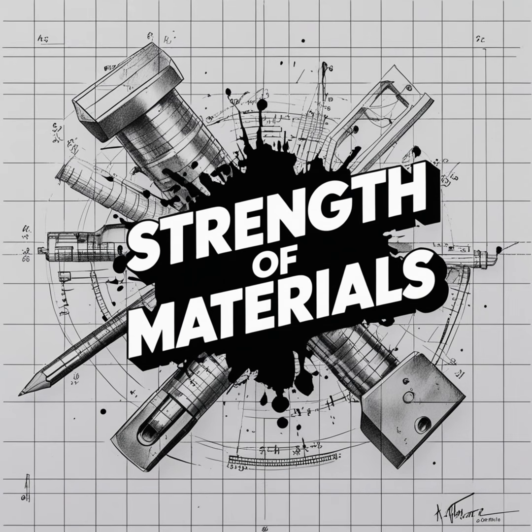Then you draw path 2. Path 2 is a massive loop drawn far away from the crack, way out on the outer edges of the metal block in the elastic region, where the stresses and strains are smooth, predictable, and incredibly easy to measure with standard, cheap strain gauges. And the math of the J integral guarantees that the energy flowing through the massive, easy-to-measure path 2 is exactly equal to the energy flowing into the microscopic, chaotic path 1. Exactly. The energy is conserved within the contour. J calculated along path 1 equals J calculated along path 2.